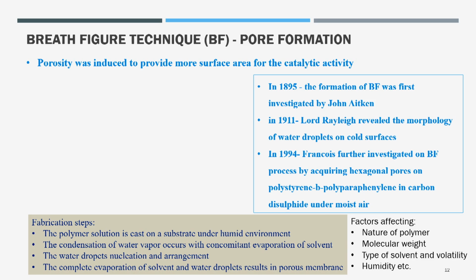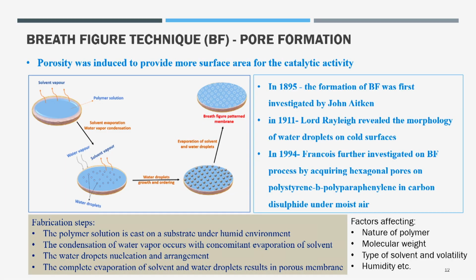A scientist comes to the conclusion of a result only with different experiments. First we went for UV-visible, which showed that yes, your sample is uniform. And what else? Then this student, Darima, was very intelligent. She said, sir, we can do a special technique to generate porosity. She made a beautiful technique. If more pores are there in the film, they are the pockets where the reactants can anchor more effectively. So she wanted to make the PLA silver system with more pores, and she made it beautifully, using a reported technique.